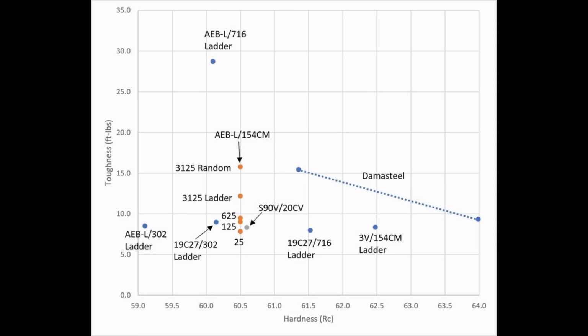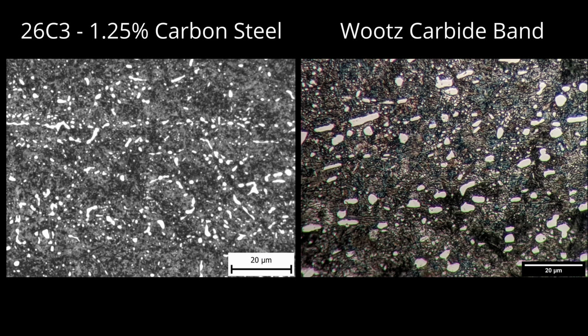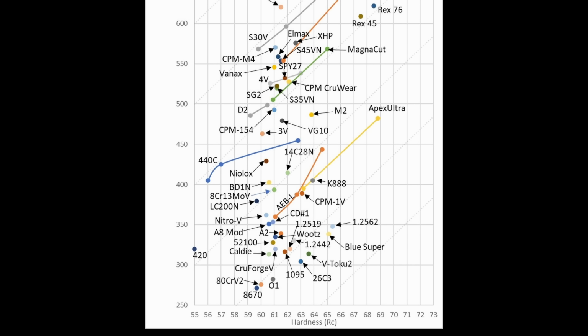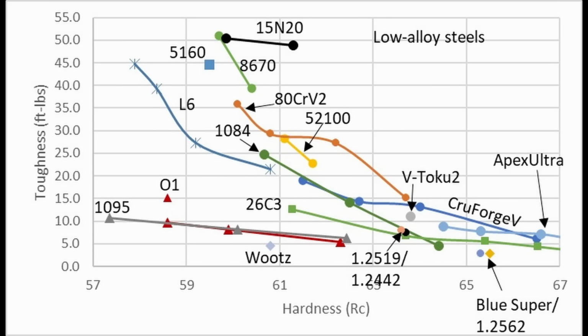I think we can say somewhat confidently that the ancient Wootz material does not match up to the properties of modern material. We can make steel cleaner, and a uniform carbide structure is typically better for toughness. The banding does help in edge retention, which is a plus. But I think if we want more balanced properties, we can make better steel today, especially if we alloy it up. High alloy powder metallurgy steels, we can have better toughness and better edge retention and better corrosion resistance than ancient Wootz. If we compare to a more similar steel, another ultra high carbon simple steel like 26C3 that has 1.25% carbon, its toughness is significantly better. 26C3 has smaller, more evenly distributed carbides.